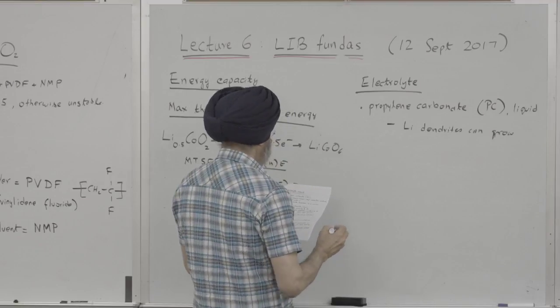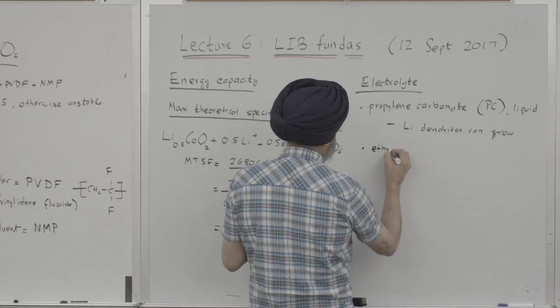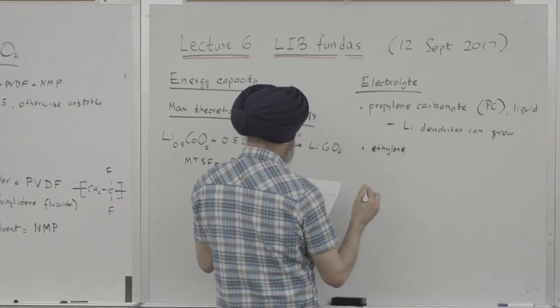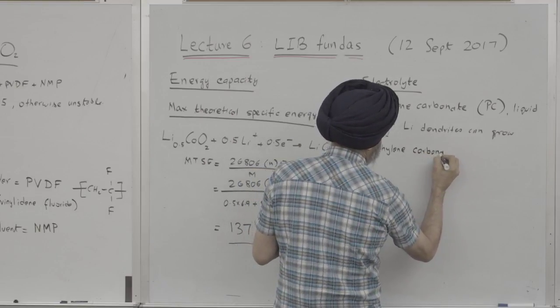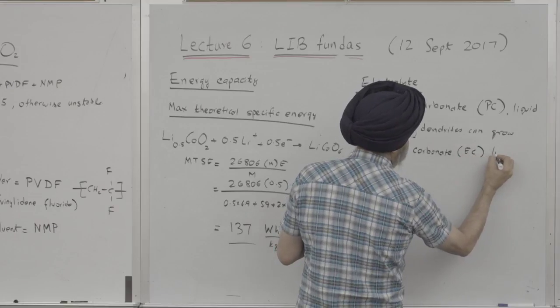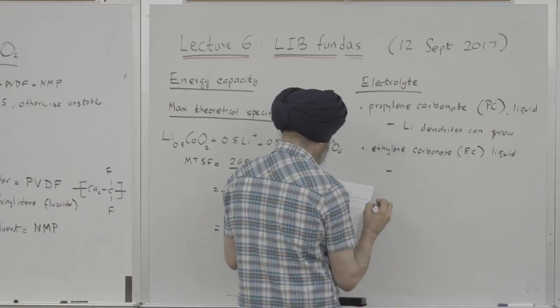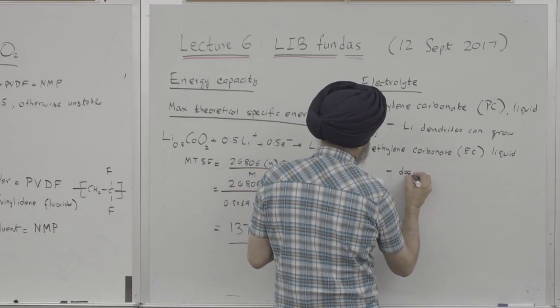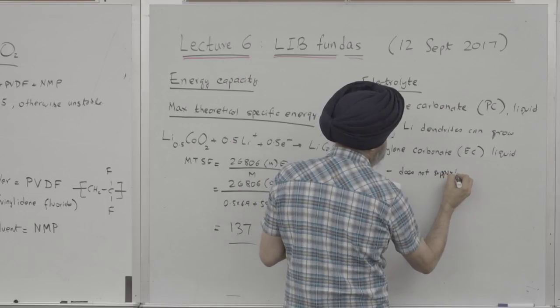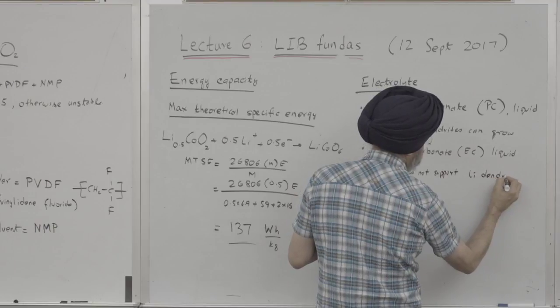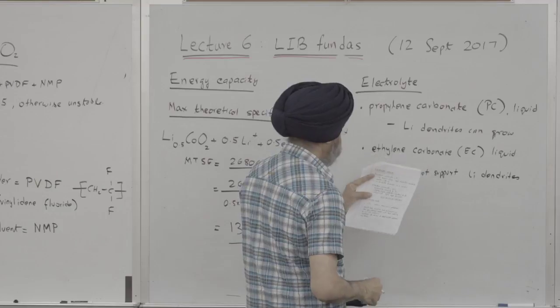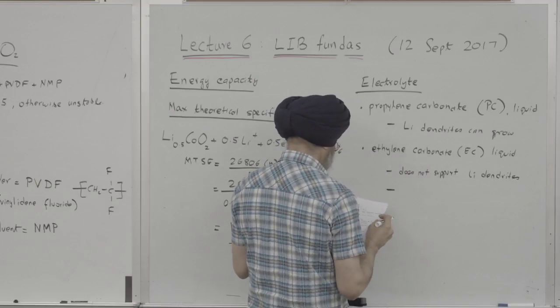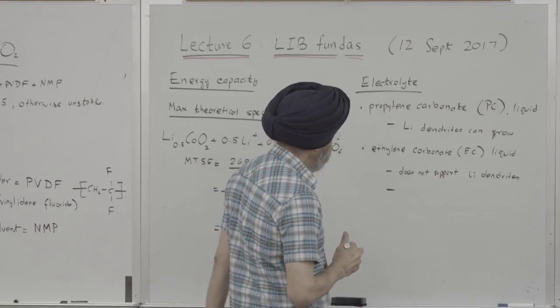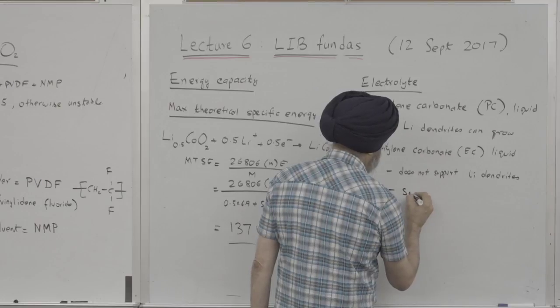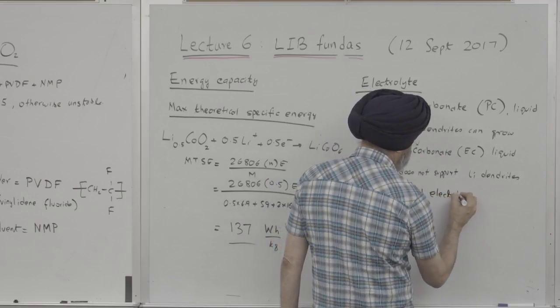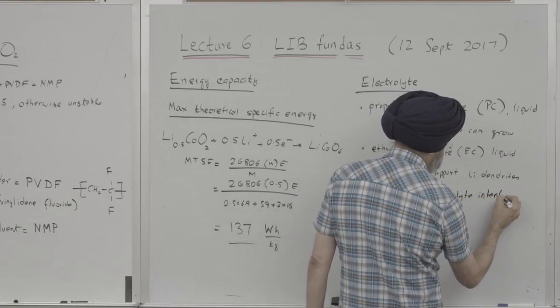And so if we have ethylene carbonate, which is also a liquid, don't ask me why, this is good because it does not support, or there's less formation of lithium dendrites, whereas propylene carbonate would support this dendritic formation. And there's another very important thing going on, and that is ethylene carbonate forms the solid electrolyte interface. So this is another important thing, SEI.